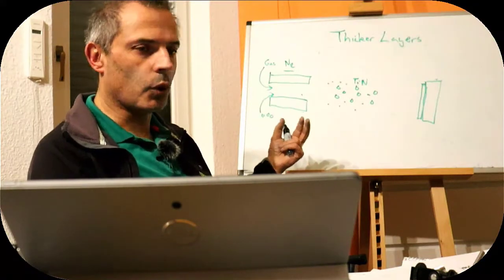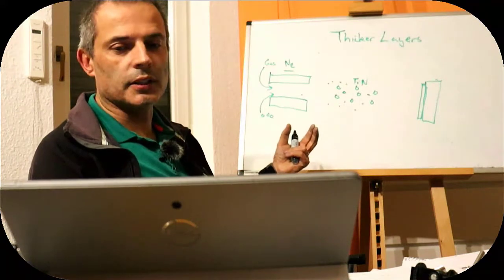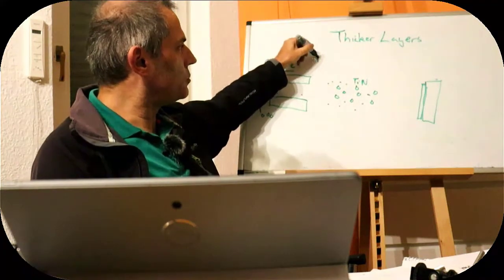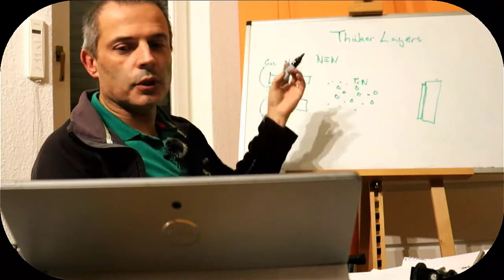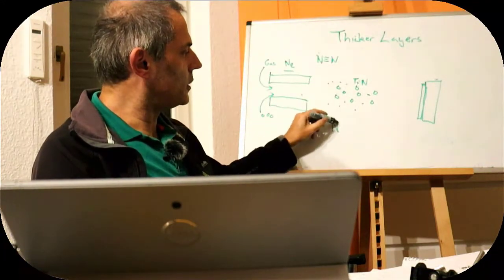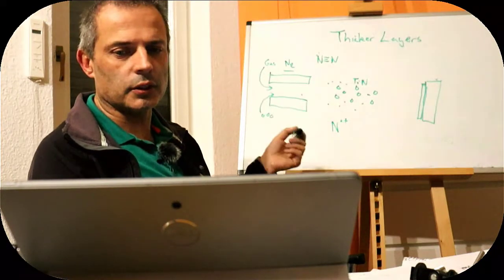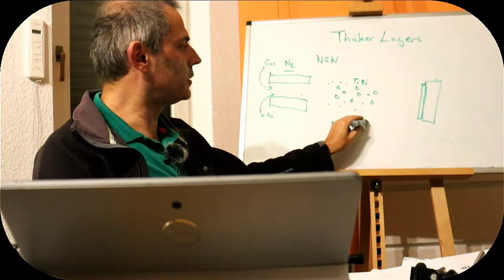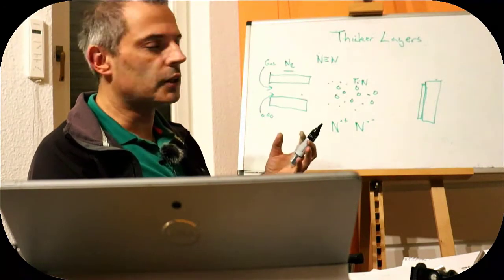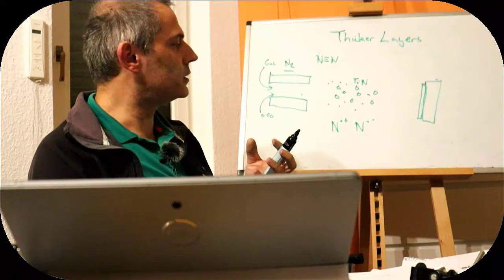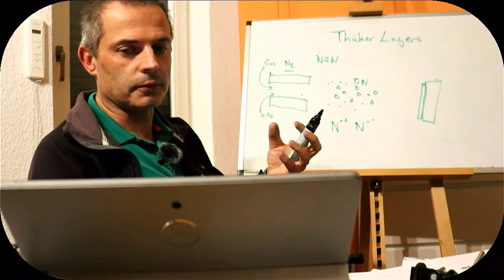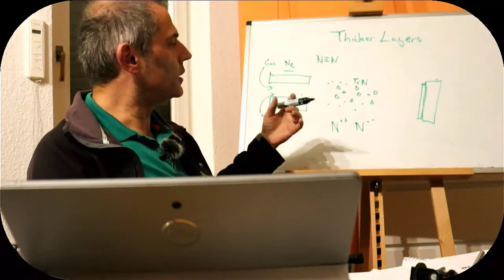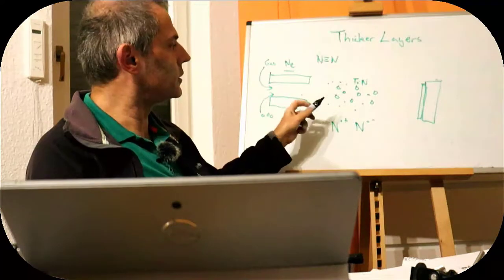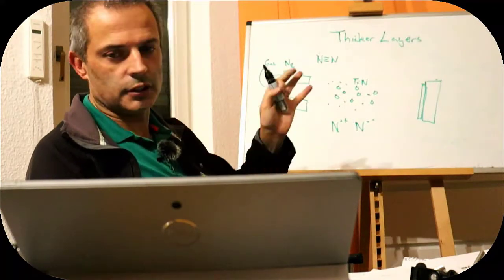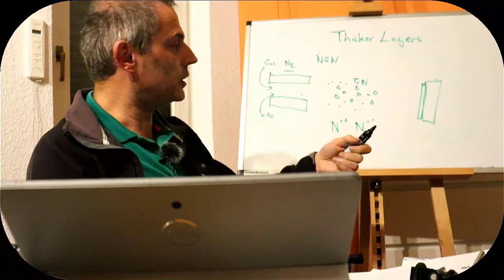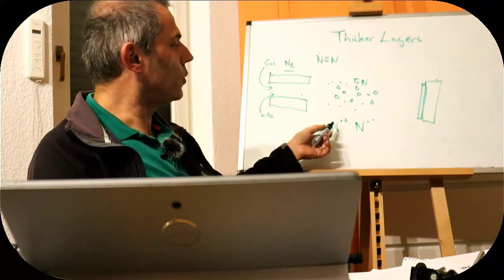Nitrogen has not that property because it's not the lightest gas, but it does have a different advantage. Nitrogen has a triple bond, and so if we break the nitrogen into nitrogen atoms, maybe make them positive as well, it doesn't really matter. Let's make the other one negative then. So we've broken our nitrogen into two ions. Then the good thing about those two ions is they contain lots of energy from the triple bond that we've broken. And so rather than ballistically whacking into our particles like the argon would have to do, they can stick to the particle and dump their chemical energy in by combining to form new nitrogen or by just bonding to